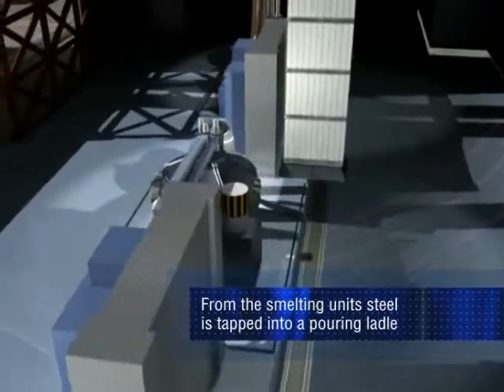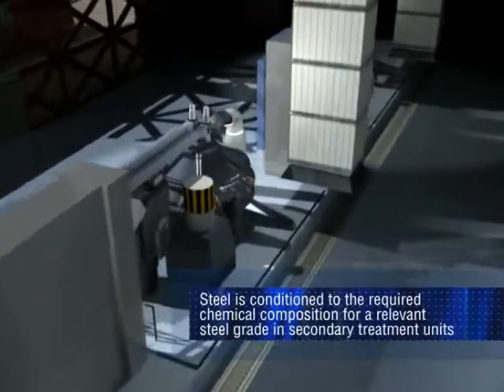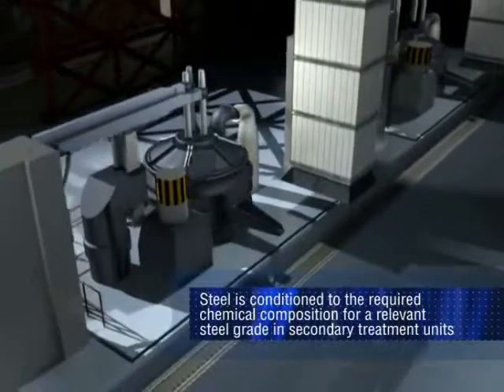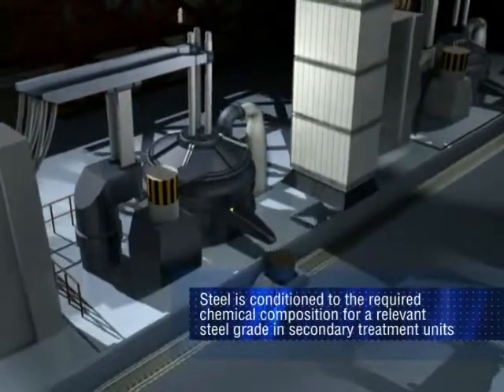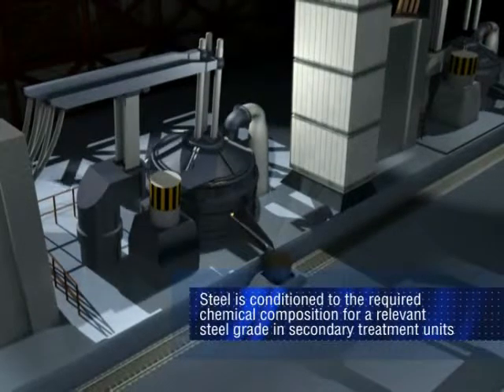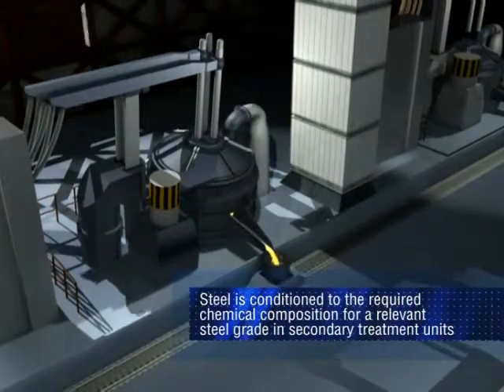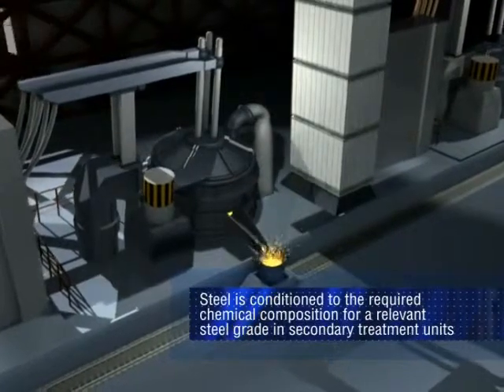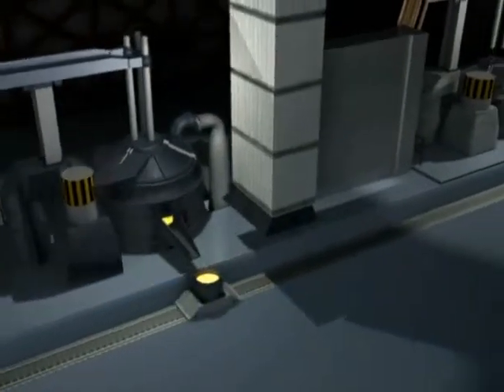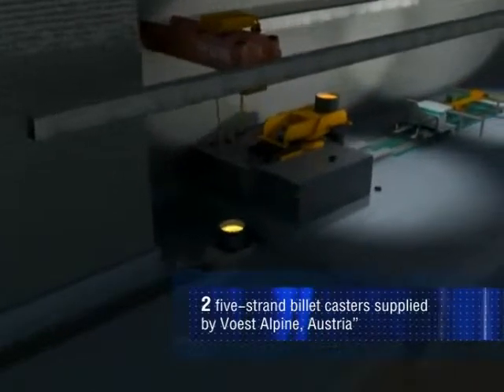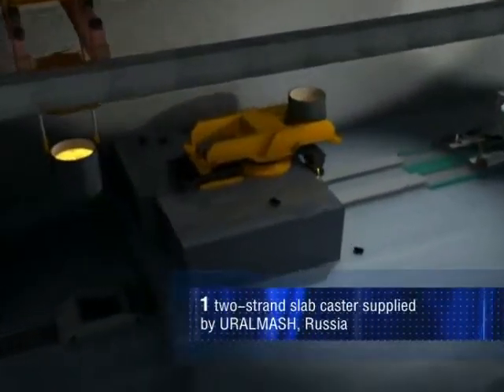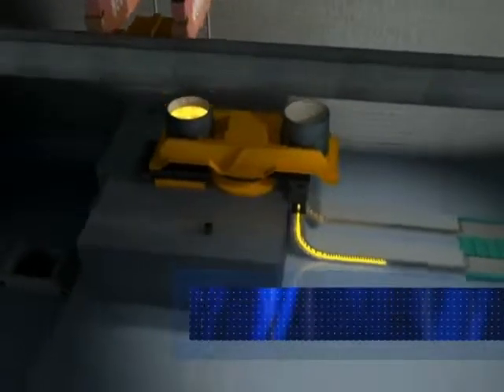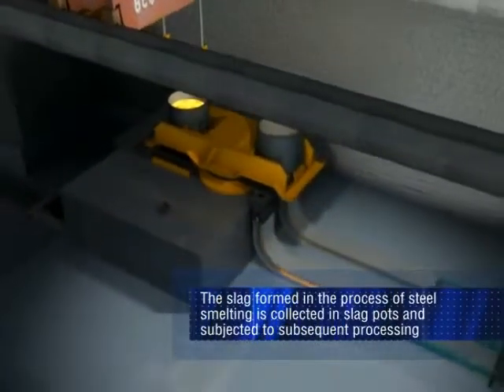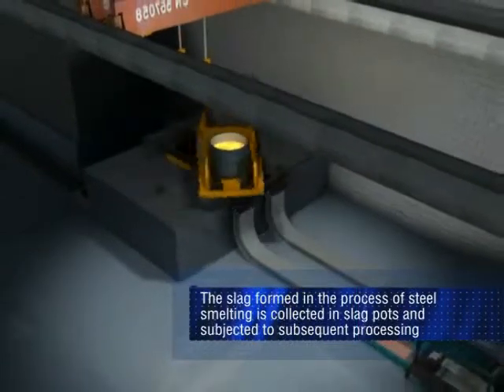From these smelting units, steel is tapped into a pouring ladle. Then steel is conditioned to the required chemical composition for a relevant steel grade in secondary treatment units, with the steel temperature at the end of treatment being equal to that specified in the order and in line with the specific casting conditions. Continuous casting is performed in 2 5-strand billet casters supplied by Voest-Alpine, Austria, and 1 2-strand slab caster supplied by Uralmash, Russia. The slag formed in the process of steel smelting is collected in slag pots and subjected to subsequent processing.